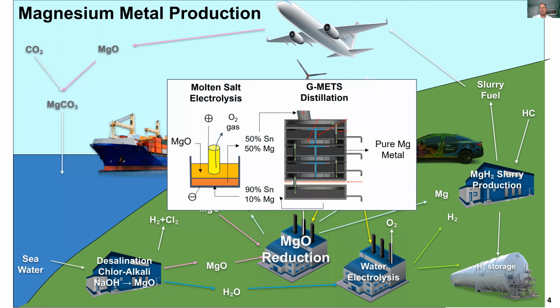Next, we reduce magnesium oxide to metal in a 2-step process. First, we use a molten salt electrolysis with a reactive tin cathode, a liquid metal cathode, to reduce magnesium oxide to make a magnesium tin alloy. This is very similar to the Hall-Héroult process, which produces nearly all of today's aluminum. So an existing Hall-Héroult aluminum plant can be converted to magnesium production. Second, a new multiple effect distillation process separates this magnesium tin alloy to recover pure magnesium metal.